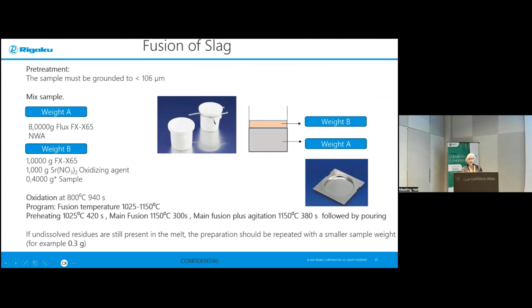So here you can see the example of how we would do a pre-treatment of slag. Why do we need to pre-treat the slag? Slag has the nature that it could exist in a glassy form or in not an oxidic form, but more a metallic form. If we directly fuse the slag with platinum, here you can see an example of a platinum mold, you will suffer from damaging your platinum, because it forms a eutectic mixture with the platinum and it can degrade the platinum, causing pits and so on. Therefore we have to introduce an oxidizing agent.